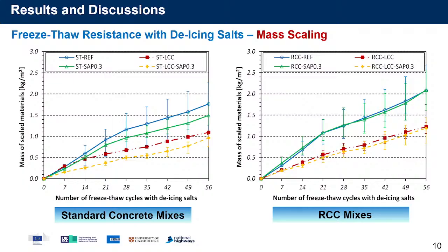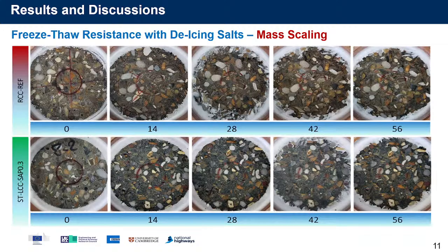The effect of superabsorbent polymer was slightly different in standard concrete mixes and roller compacted concrete mixes, and it has negligible impact in RCC mixes. And the best performance again was achieved in the mixes where we had used both materials at the same time.